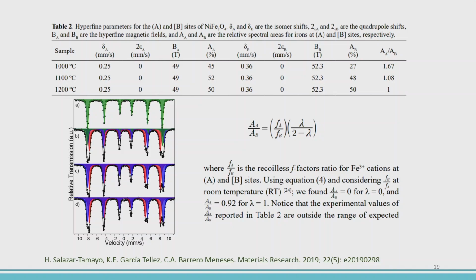We notice that it can also be explained as we explained before: the samples at low temperature, let me say 1000, have cation vacancies, but as temperature increases, there is a filling up of these vacancies. It's not due to cationic distribution, as is assumed here in this formula. This formula can be obtained from the previous formula and is also published in the literature. We found that when lambda equals 0, this ratio is equal to 0.